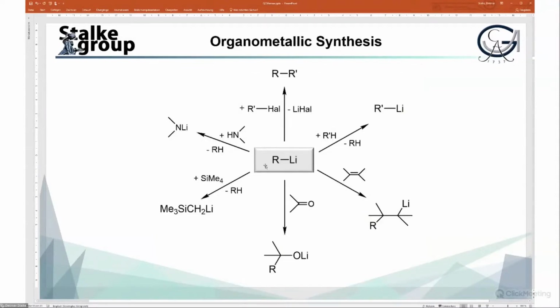You can start with lithium organics right in the middle and then add an aryl or alkyl halide, and then you precipitate out lithium halide to connect a C-C bond. And that is in drug design almost the last step where you can have stereo and regio selectivity. If you want to use the lithium organics as a base, then you deprotonate a starting material. You're losing butane or methane, which is very clean, and then you get a very clean product. You can add lithium organics across a double bond, and you can do that stereo and regio selectively. And you can add that across a carbon-oxygen or a carbon-nitrogen double bond to end up with an amide or an alcoholate.